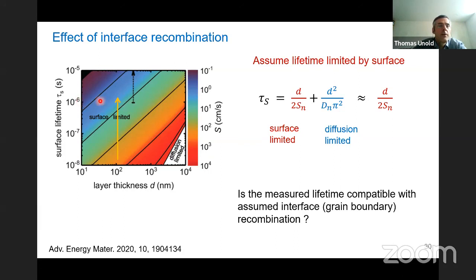So if you measure on a cell or an absorber, actually, with grain sizes of 100 nanometers, you measure microsecond lifetime, then your interface and your grain boundary velocity can be not larger than 10, basically. And I've often seen that when different measurements were made with different techniques, they concluded a very high surface recombination velocity, but then they showed also very long lifetimes, and that doesn't mix. So that's a consistency check that's very good to do.